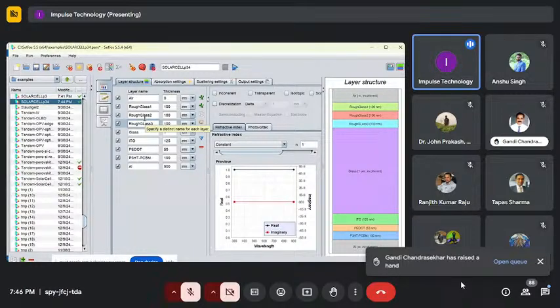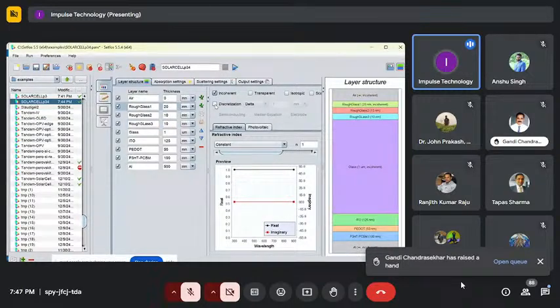So we use effective medium approximations, which generally means that the surface roughness has partial coherence and partial roughness. So we will be considering the effective medium approximation here. You can change the thickness. It is incoherent, so I am considering that here. We do not want more discretization, so I am only considering 5 elements.